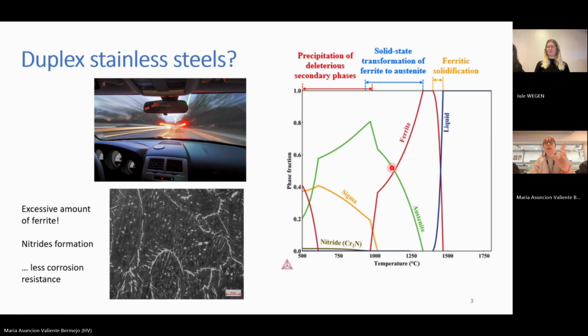Here you can see, I forgot to say, everything that you will see white in these microstructures that I'm showing is the austenite, and everything darker is ferrite, and everything super dark is the nitrides. So these nitrides are chromium nitrides, and they gather a lot of chromium around, so that depletes the corrosion resistance.